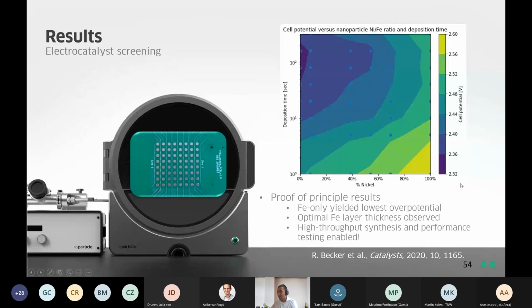If we superimpose these two plots on top of each other, what we have here is the cell potential: if we go from light green to dark blue, we go to lower cell potential, so a more efficient electrocatalyst. And what we find here is that an iron-only catalyst with an optimal layer thickness was the most efficient electrocatalyst for this particular system. And this confirmed that we were able to prepare electrocatalysts in high throughput and also study them in high throughput.